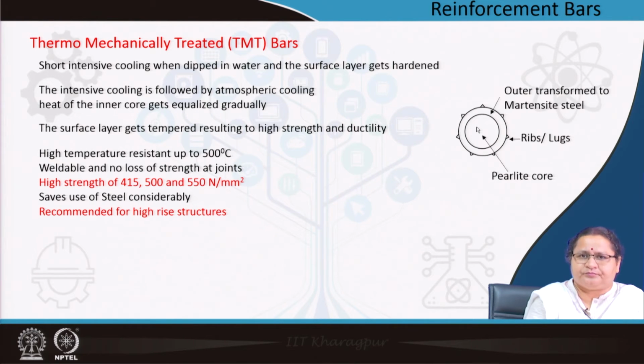These thermally treated bars or the TMT bars are weldable, and at the point of welding it does not have a loss of strength. We can get high strength starting from 415 Newton per millimeter square to up to 550 Newton per millimeter square, and around 40% of use of steel can be reduced and hence recommended for high rise structures.